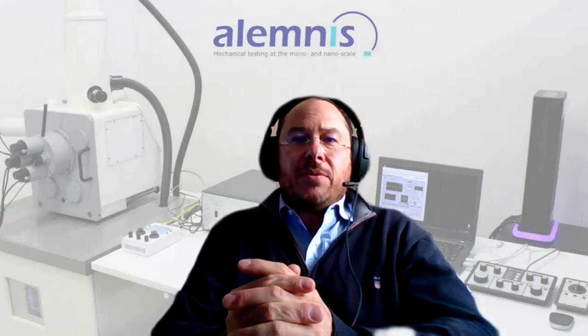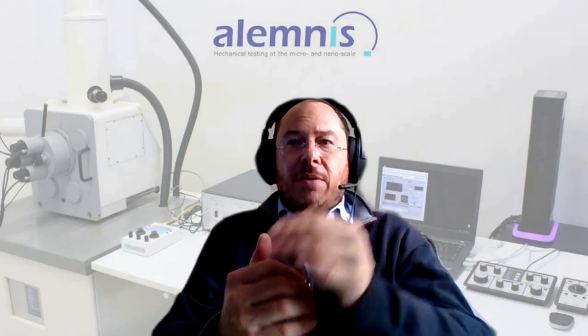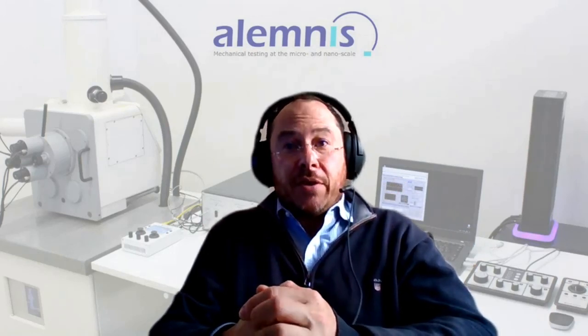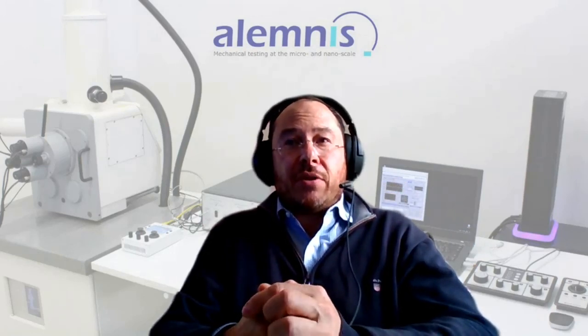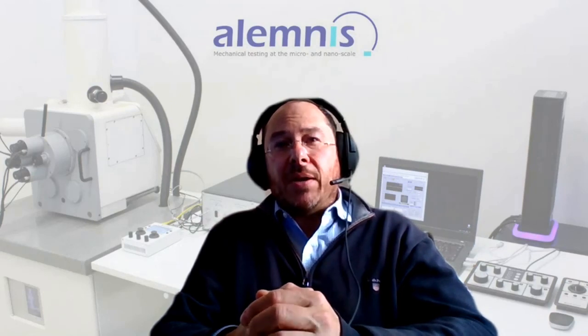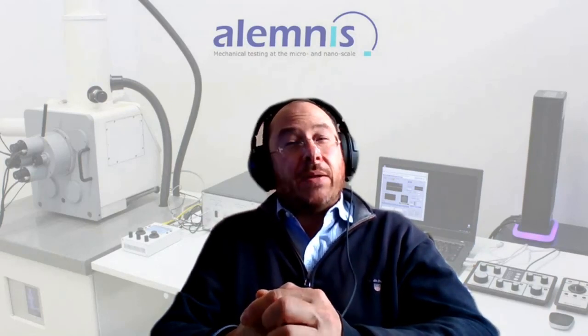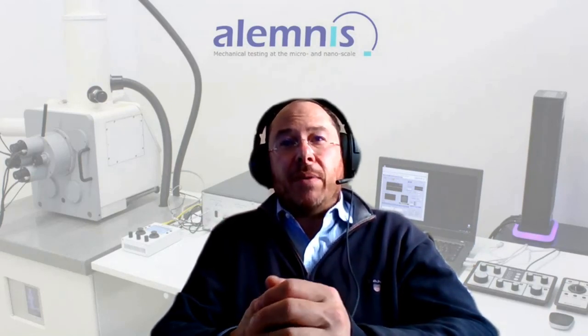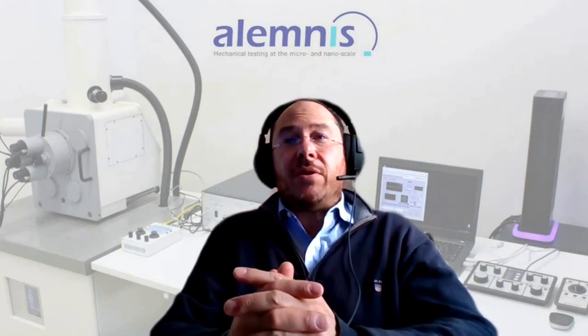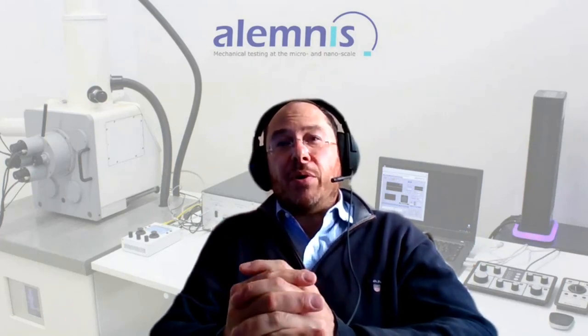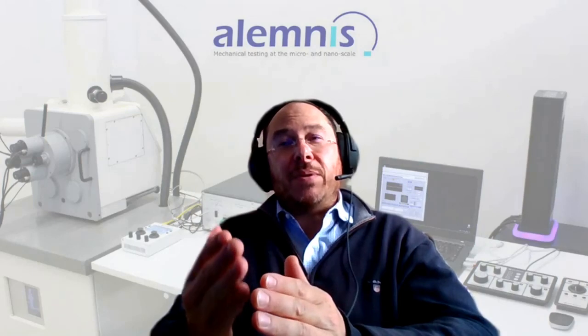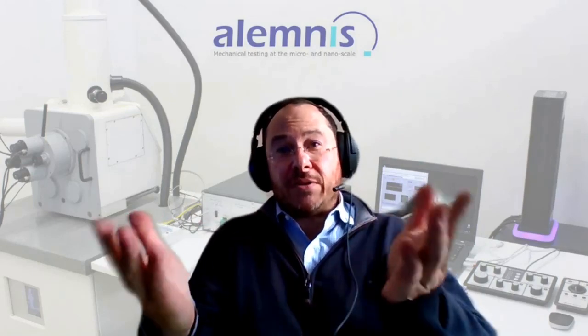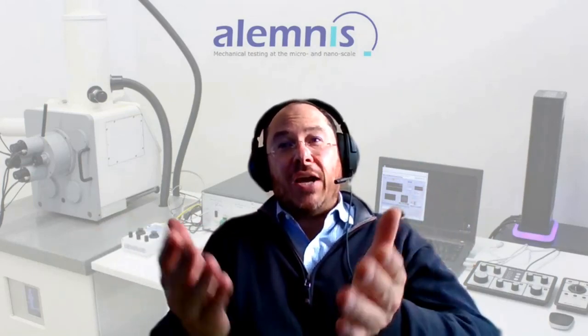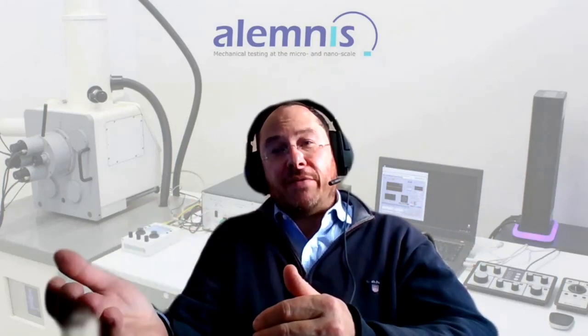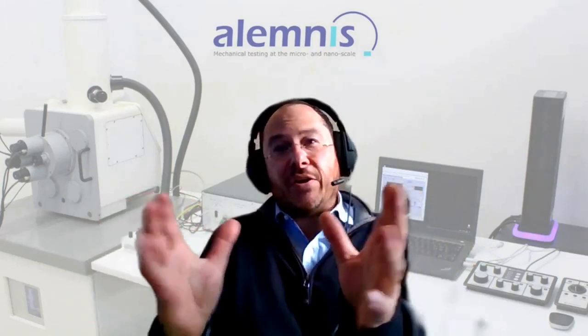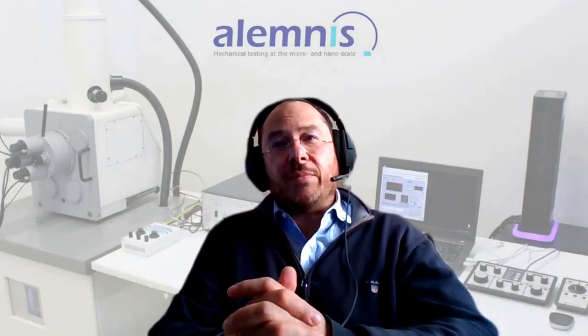It depends on the two materials, the coating and the substrate themselves, and how thick the coating is. As a general guide, we try and keep the depth limit to about 10% of the coating thickness, but in many industrial applications, this is not possible. So we want our indentation depth to be deep enough to overcome surface roughness, but shallow enough not to have the effect of the substrate. So it's really a compromise depending on your particular material.